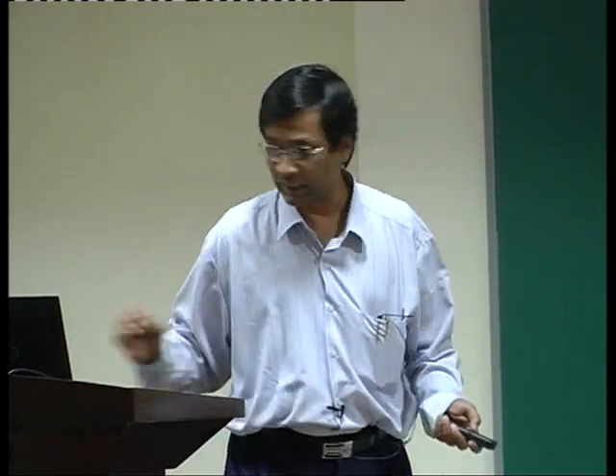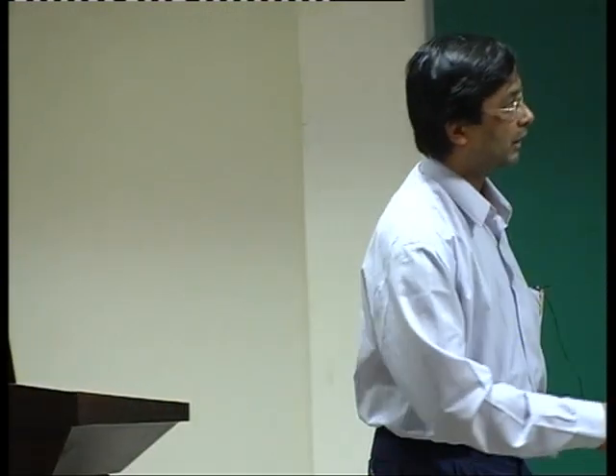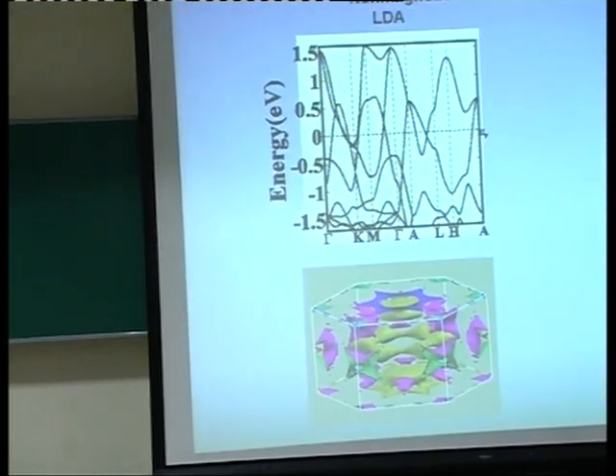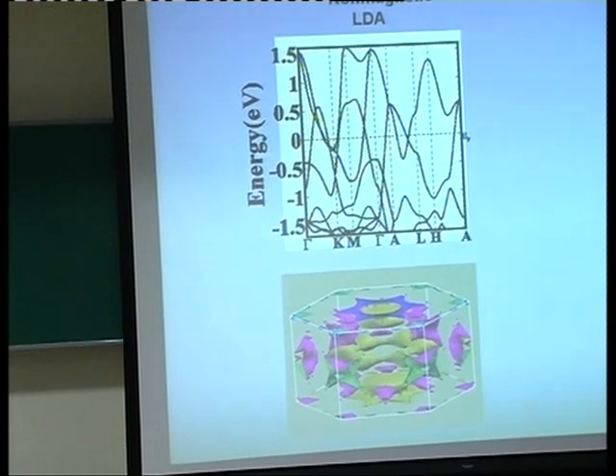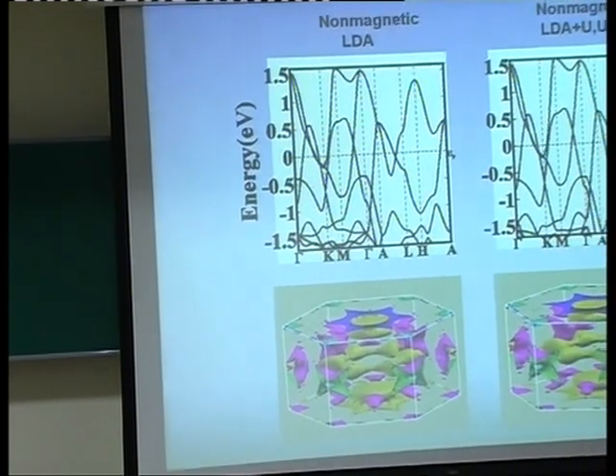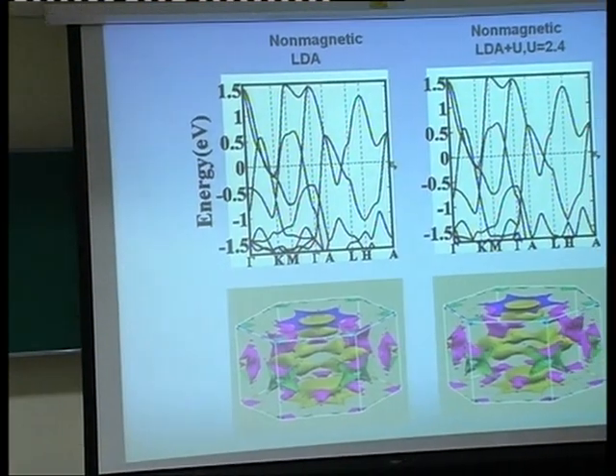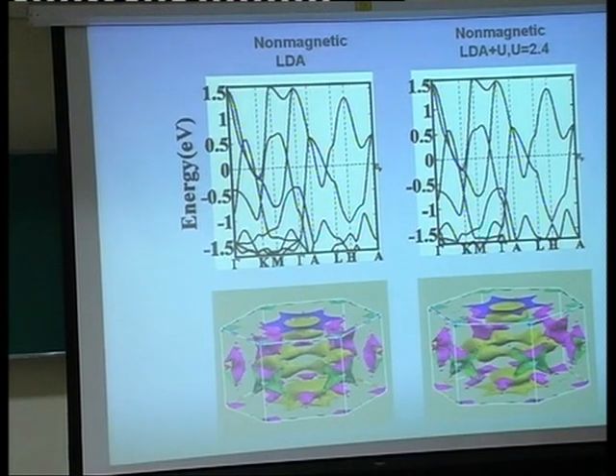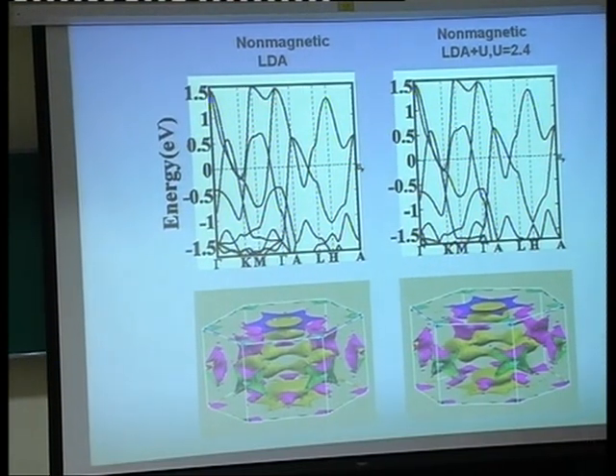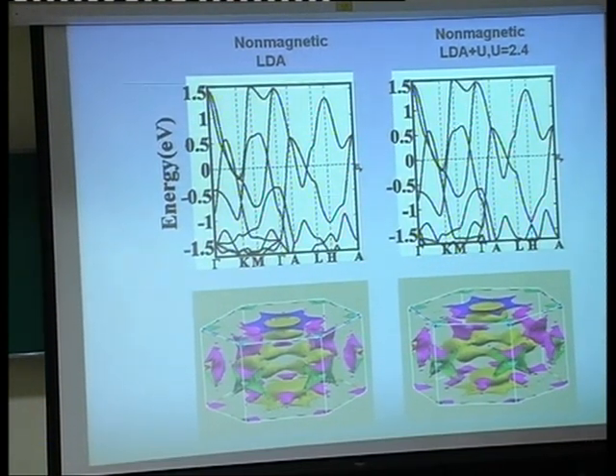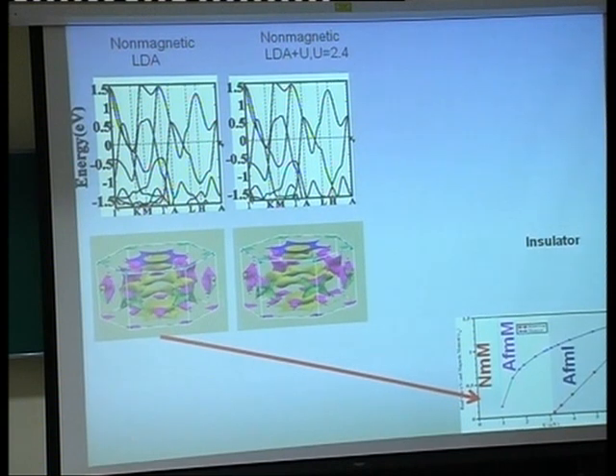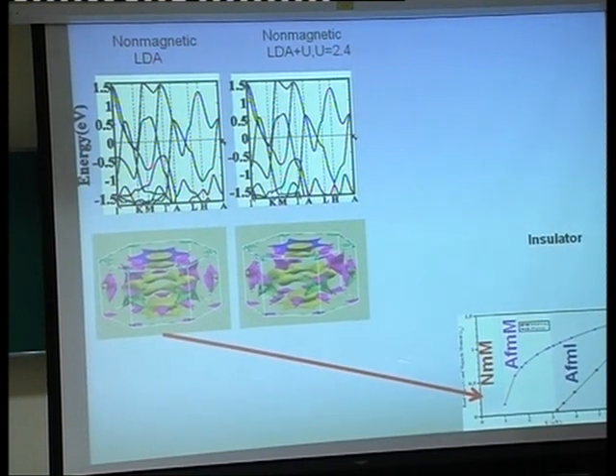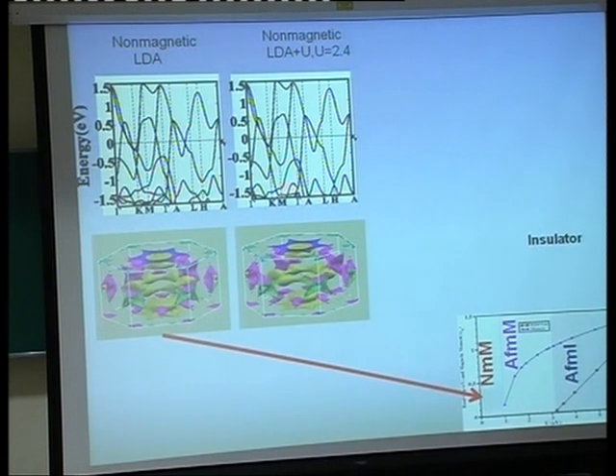So this is the LDA, without any U value, the paramagnetic metallic state, and the very complex Fermi surface that I've shown over here. We can increase the U value, largely by 2.4 electron volt, keeping the non-magnetic state, and you'd see that hardly anything has happened. There's absolutely no change that really happens. Okay, so what we are showing is that this is the one that I just now showed you. So this one belongs to this non-magnetic metallic state.